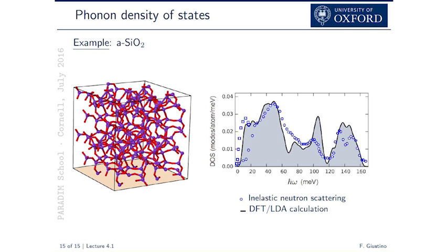One is that this is a model of an amorphous solid, so nobody gives us the coordinates of an amorphous solid. This has been determined by many calculations and many studies, essentially by making sure that the short range and the medium range structures agree with various experimental probes. So that's one of the best models we have now. But there is no guarantee that this is perfect. So we're not comparing a crystal with a crystal. What I'm trying to say is the blue circles correspond to a structure which we don't know yet. So we just hope that this is a good model.